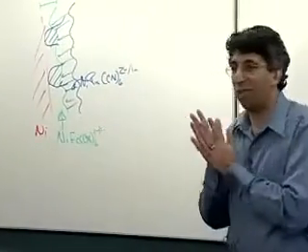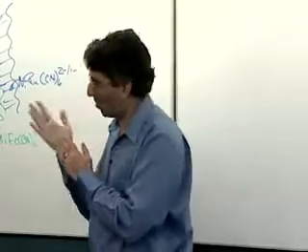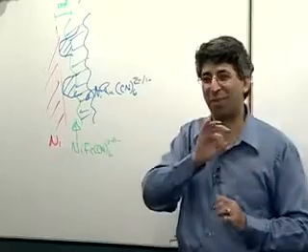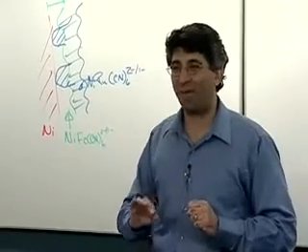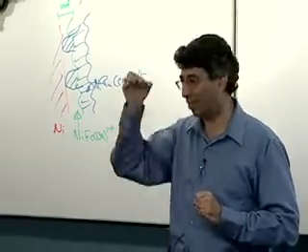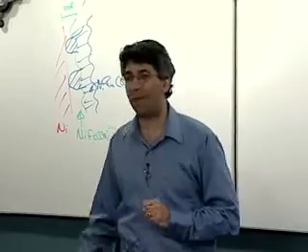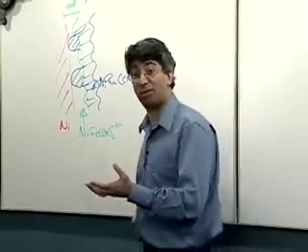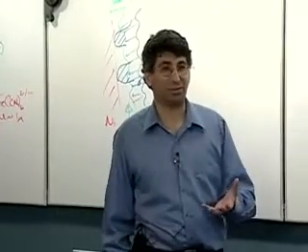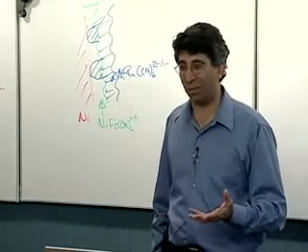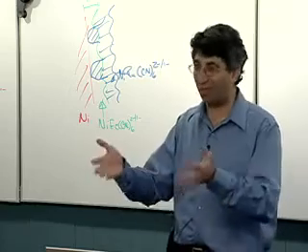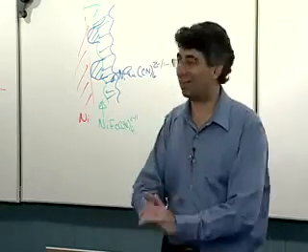And so the first thing we did is we did the brute force approach, which was we made up 50 of these electrodes. We made up an electrochemical cell with a volume of 1 milliliter, and we ran each electrode, cyclic voltammetry. We cycled it for 30 minutes for 50 electrodes in the same volume of solution. And then we looked for ruthenium in the solution by atomic absorption. And we found about 0.1 parts per million of ruthenium in there after all of this, and said, this is not enough to do that, and this is after running this thing with 50 electrodes in it. How could we ever see it with one? So that didn't sound too good.